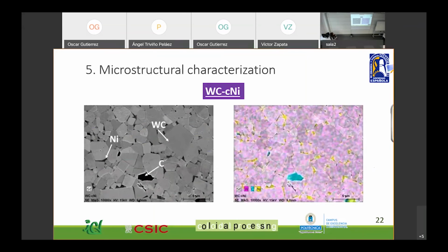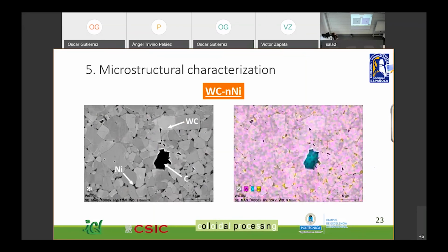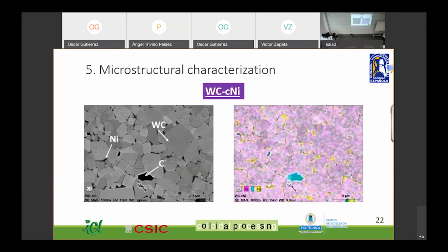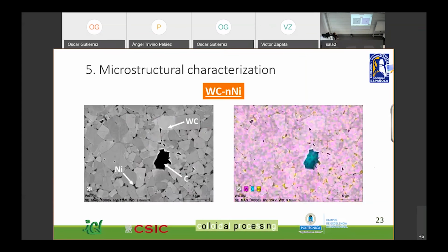And finally, just to finish with the microstructure characterization, we carried out some EDX mapping analysis of the polished cross-section of our samples. And as you can appreciate, I hope, in both mixtures, we can see that nickel is just located on the grain boundaries, and there are some graphite precipitates, these agglomerates all over the microstructure.